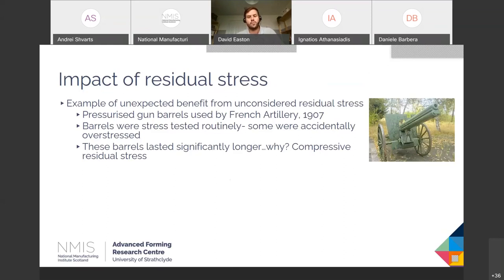The reason was compressive residual stress. When they'd overstressed that inner bore of the gun barrel, they'd accidentally introduced residual stress. And that was a fatigue sensitive part of the component, and in actual fact, increased its lifetime.